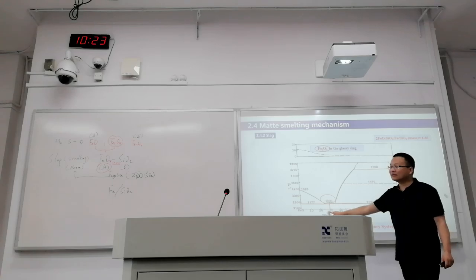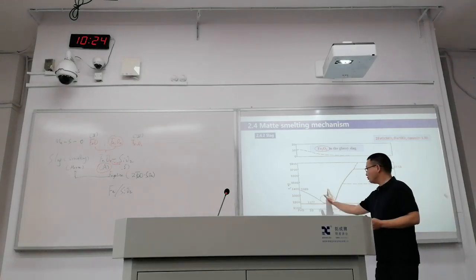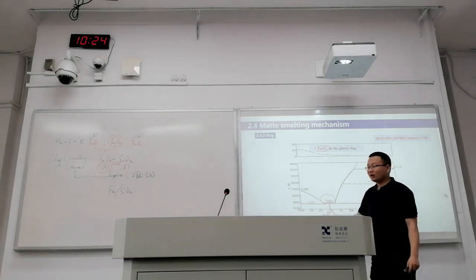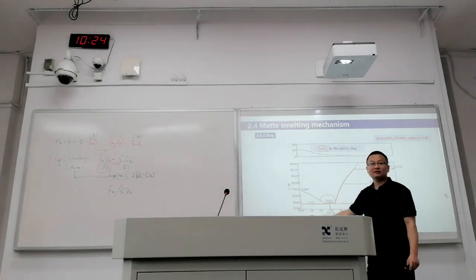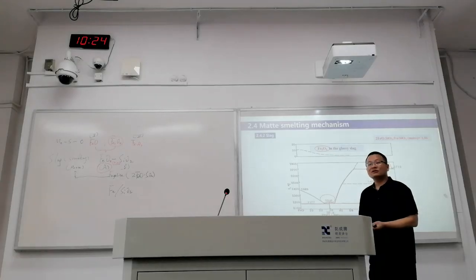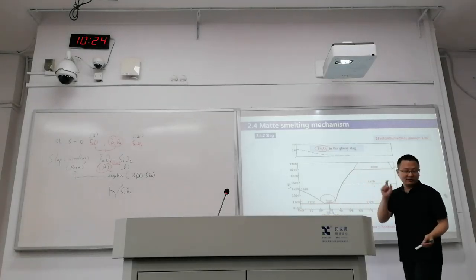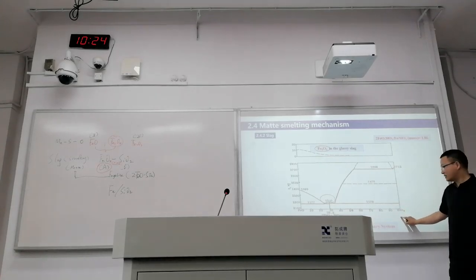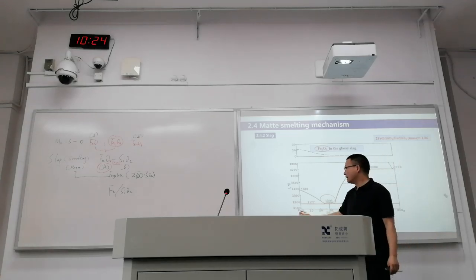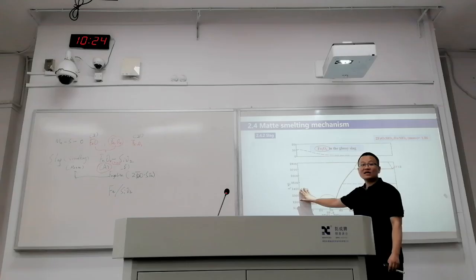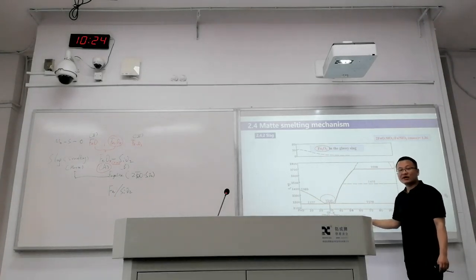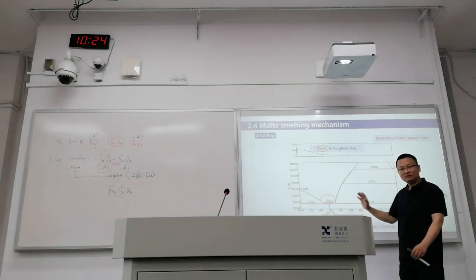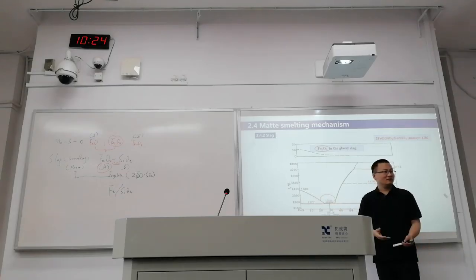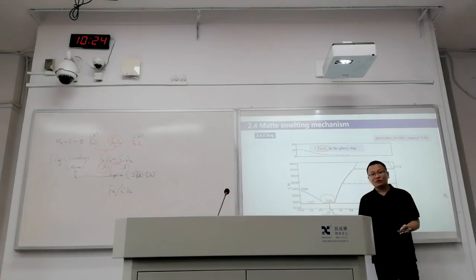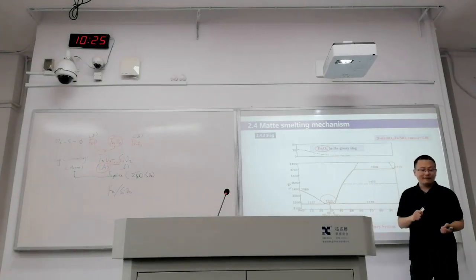This is fayalite. And when we are starting, the interesting part is we will have two directions. Originally we are somewhere here. We have a lot of iron oxide because we are starting from concentrate. Iron will be oxidized, so we only have a large amount of iron oxide and a very small amount of silicon associated with the concentrate, right? If we are not adding anything, there's only a small amount of silicon but a large amount of iron oxide, so we will be somewhere here. We agree? And when we are adding more silicon oxide as flux, we will move in this direction, the right direction. So the liquidus temperature will be decreased. This is the magic. This is the strategy. We are using this to reduce the liquidus temperature.